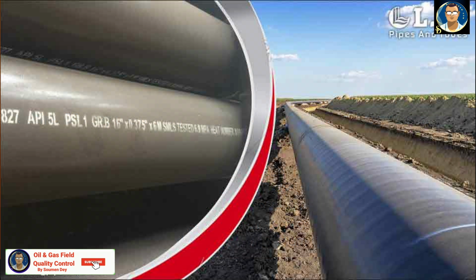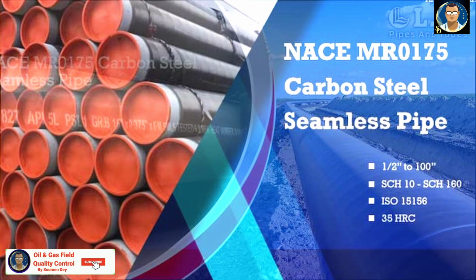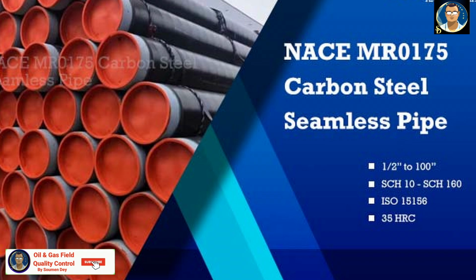Sour service pipe definition. Now we will see what are the special requirements for sour service pipe. Sour service pipe is mainly used in H2S environment, where H2S or hydrogen sulfide is a harmful chemical that easily generates corrosion. According to international regulation, when partial pressure of hydrogen sulfide reaches 300 pascals, the line pipes used shall have anti-acid corrosion performance. So, sour service pipe includes NACE pipe.